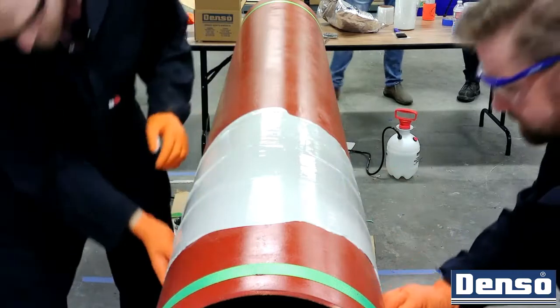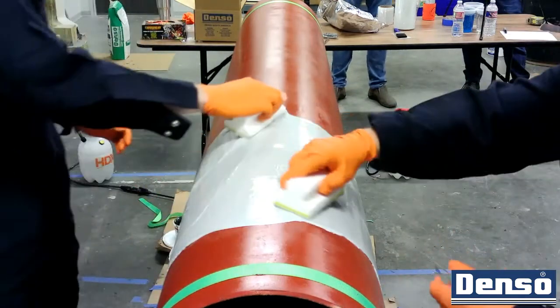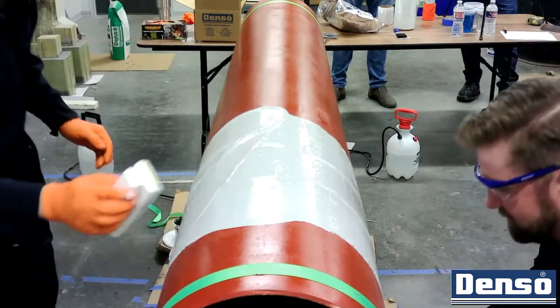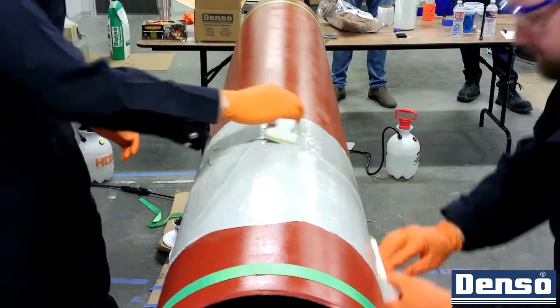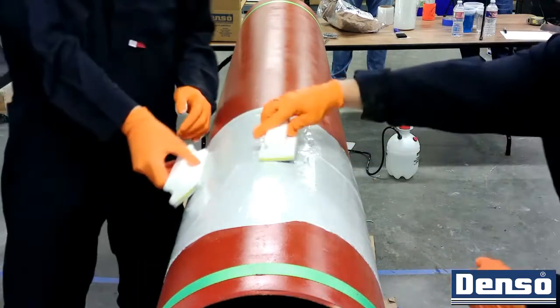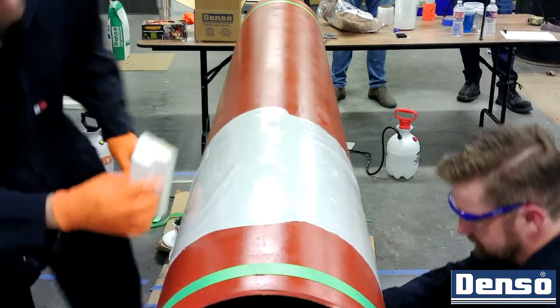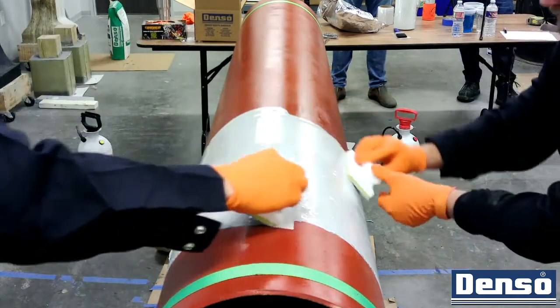The epoxy will increase the adhesive strength of the bore wrap on the leading section when it is applied wet on wet. We can apply the bore wrap directly onto a wet epoxy in this case because it is simply being used as a primer over an already existing anti-corrosion layer.